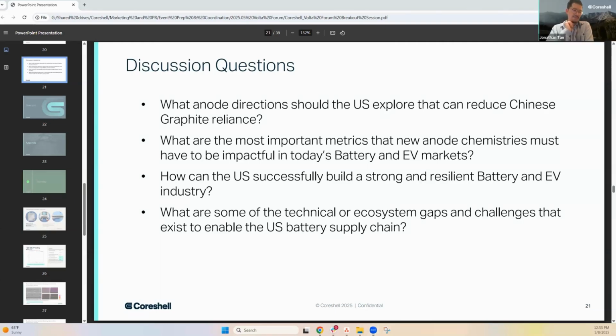Yeah, agreed. That's the reason why we've been demonstrating in a full cell, Jay. I completely agree with you, which there is really no such thing as a like for like drop-in replacement, in my opinion, in lithium-ion batteries. The whole system kind of works in a sort of complete package, right? Exactly right. We're using, for example, a pure silicon. That's going to be very different than a silicon carbon or an SiO product. The chemistries, the reaction against the electrolyte is completely different. The surface chemistry is completely different. And so what we are working on is demonstrating the whole package.